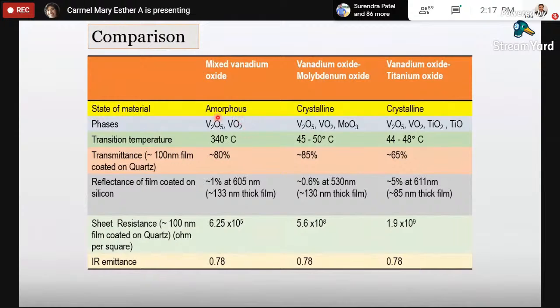For example, if we have only vanadium oxide, it is in an amorphous state, and we achieved a transition temperature in the range of 340 degrees centigrade. When we composite it with molybdenum oxide, the transition temperature drops to 45 to 50 degrees centigrade, and when it is composited with titanium oxide, we got a transition temperature between 44 and 48 degrees centigrade. From this we understood that tuning the transition temperature is a big challenge for us. As soon as the transition temperature drops, we observe transmittance compensation also. The vanadium titanium oxide composite shows a very low transition temperature, but we have lost about 15% of the transparency.